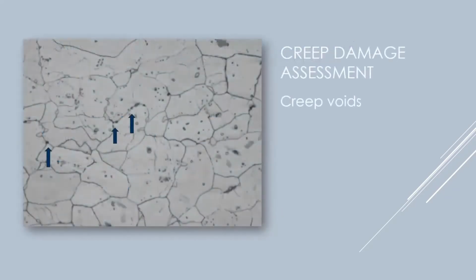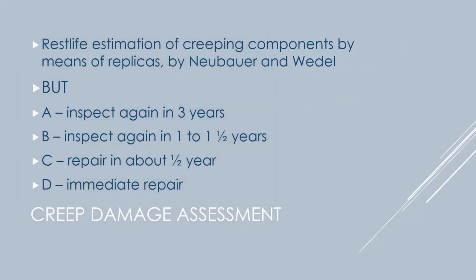So if we go back to that one there, if all we found was things like that on the left-hand side, you'd inspect in 3 years. That one in the center, every 1 to 1.5 years you'd go back and re-inspect that boiler tube. And C means you can probably run for a little while. You're going to have these microcracks about the size of a grain. You can probably run for half a year before you have to do your repair.